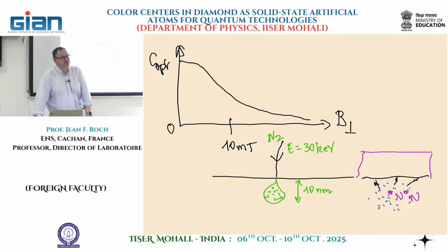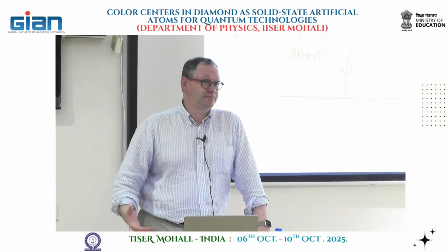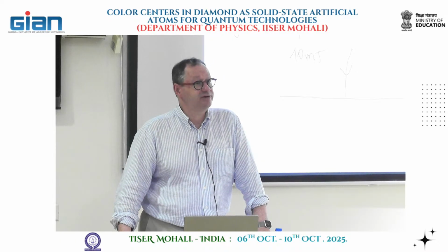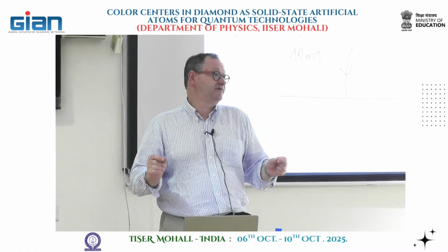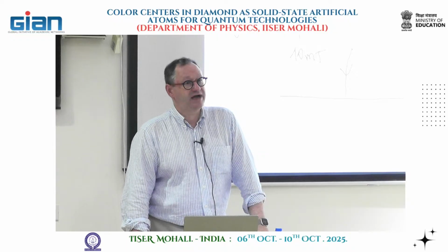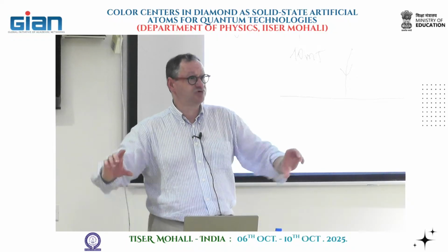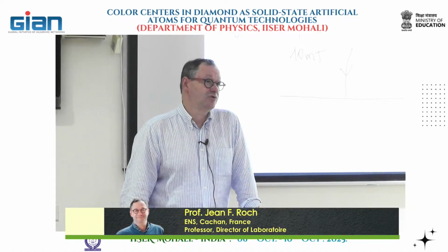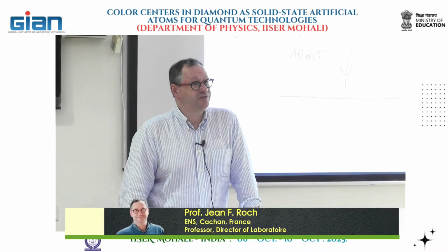Well, it works. Unfortunately, it's again the problem of getting indistinguishable single photons from a single NV, which is difficult due to the poor rate of emission in the zero phonon line. So another, more efficient way to implement that is to look at the silicon-vacancy center. They have narrow emission if you put them at a few Kelvin, and then you can hope with them to have indistinguishable photons and also to couple them to cavities. So we're closer to what people are doing in quantum dots.